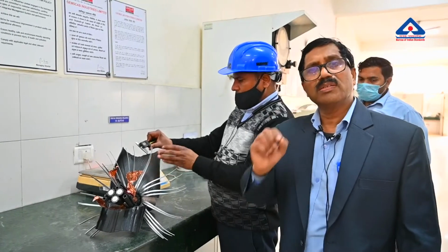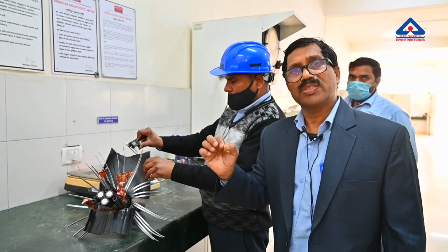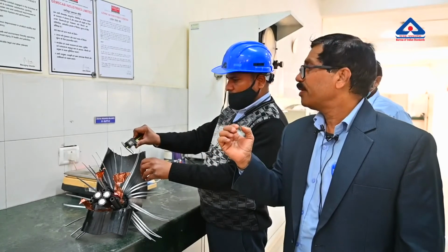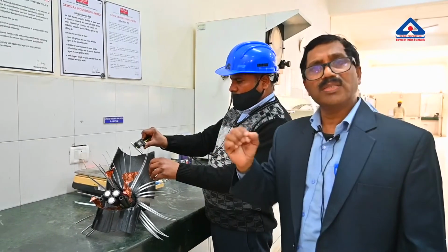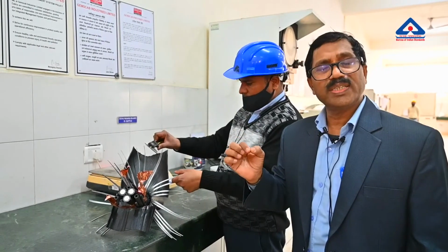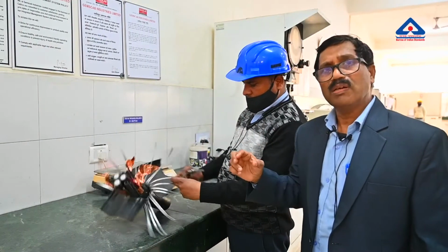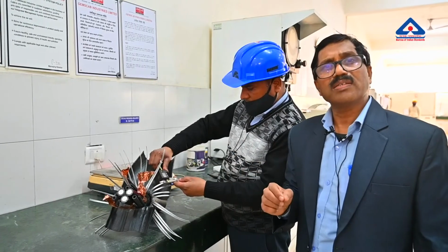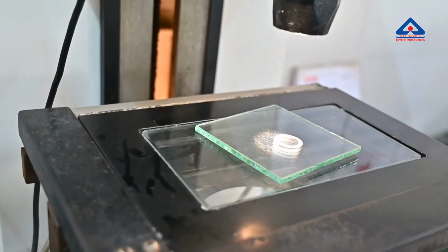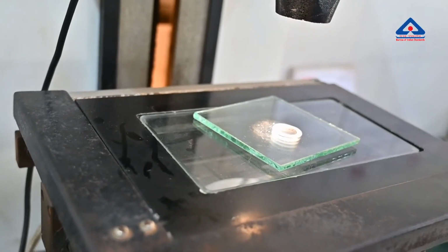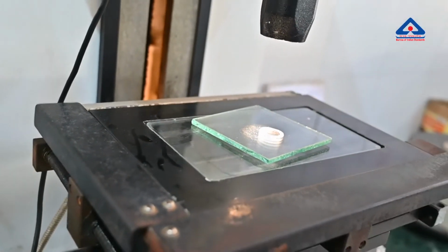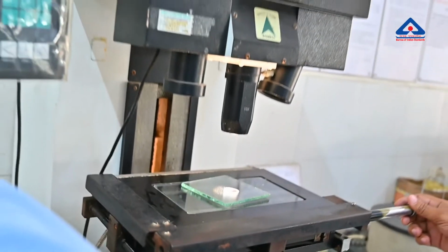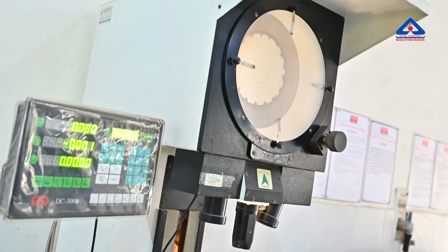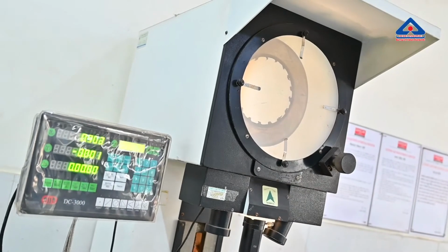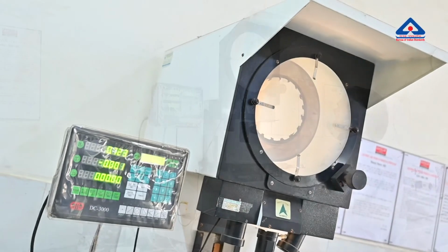We are going to measure the thickness of outer sheath, and it is coming 3.14 against the requirement of 2.6 minimum. After that we measure the armor dimension. For the measurement of insulation thickness, we are using the profile projector. We will measure the thickness of conductor screen, XLP insulation and insulation screen. It is 3.62 for the XLP insulation layer. Insulation screen is 0.66 mm.